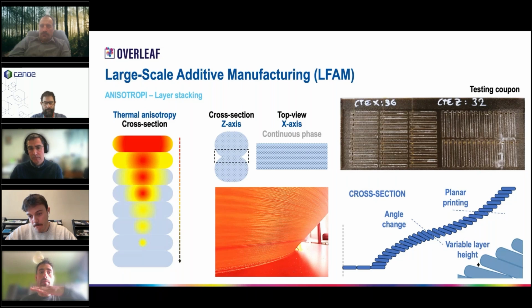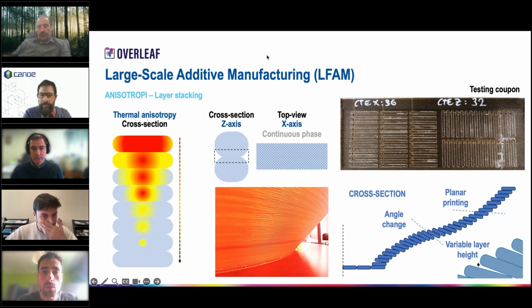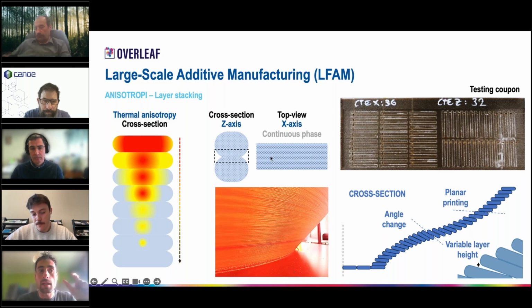What does this mean? Remember, we are stacking one layer on top of the other, and that is generating 2 completely different axes. On one side, we have an axis in which different layers are stacked on each other, generating an interface. This is not continuous. However, if we watch from the top view, what we print is a completely continuous phase. And if we remember corn stover, we have inside our material fibrillar structures, which are usually aligned along the x-axis. That is generating 2 completely different behaviors in our materials.